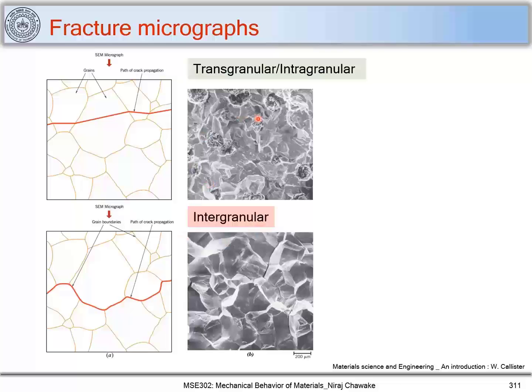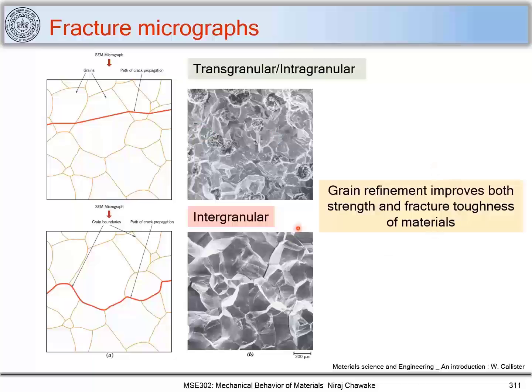And these are the typical micrographs which indicate a transgranular or intergranular fracture. So you can see that the crack would have propagated through boundaries. You can see here that it is propagating through boundaries. However, in this case, you can clearly identify that the crack would have propagated through grains. In this case, you can say that grain refinement improves both strength and fracture toughness of material.